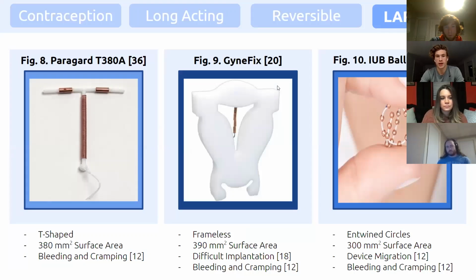As mentioned before, the Paragard T380 is the only FDA-approved copper IUD in the US, but novel designs have been implemented in other countries. Gynafix is a frameless IUD that is attached to the myometrium of the uterine wall. Its increased cupric surface area and implantation method make it unlikely to solve the problems with Paragard. The IUD ballerine is composed of a polyurethane frame common to Paragard and most hormonal IUDs, but has 2 entwined circles with balls of copper dispersed along the frame. Its surface area is an improvement over the Paragard IUD, but is still susceptible to the burst release of copper ions and results in increased device migration.